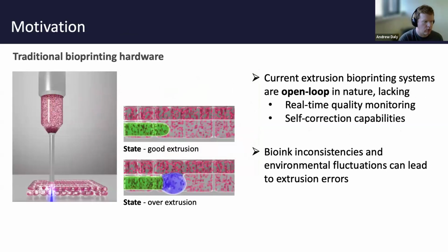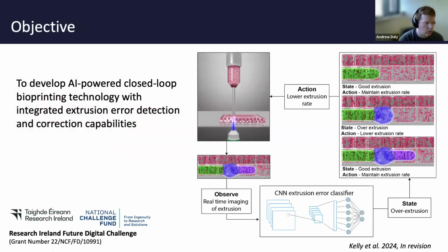So we have another project ongoing now where we're trying to monitor the extrusion process in real time. For example, if we have correct extrusion happening for a period of time, and an error does occur, could we then in real time adjust that and fix it or lower the extrusion rate in this case? So we're developing a system where we observe the printing process using cameras. We're using convolutional neural networks to classify if the state is good or bad or appropriate over time. And say if we've detected an over extrusion, then the plan is, could we implement an immediate correction after that?